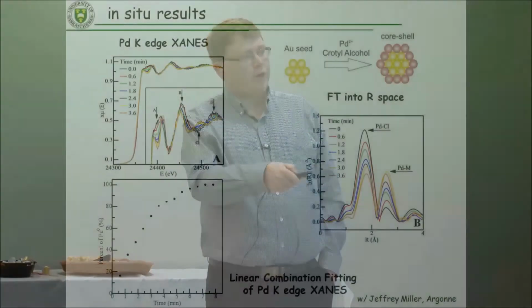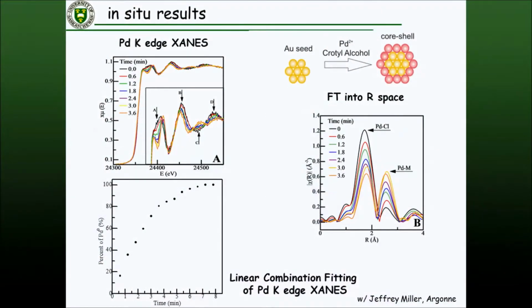But you can see that the palladium chloride band is dropping down and a palladium gold band is rising. Again, really good support for the idea that the palladium chloride is being reduced onto the surface right at the beginning of this reaction when we start with palladium salts.